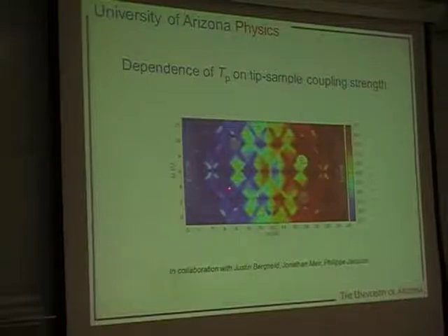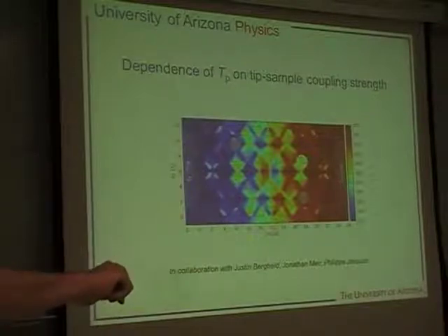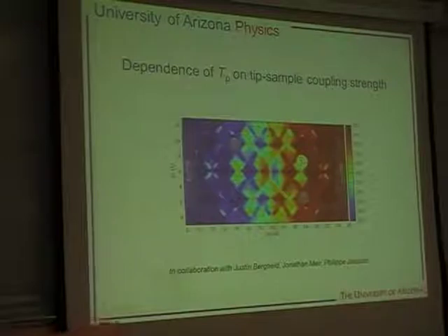So here, again, is a graphene nanoribbon with a thermal gradient across it. And now I just want to look at the temperature at these 3 points, a cold point, a hot point, and a point with intermediate temperature. And I'm going to keep the temperature probe fixed in position, but I'm just going to, by hand, vary the strength of the coupling between the probe and the sample, just to see if the temperature depends strongly on this coupling.